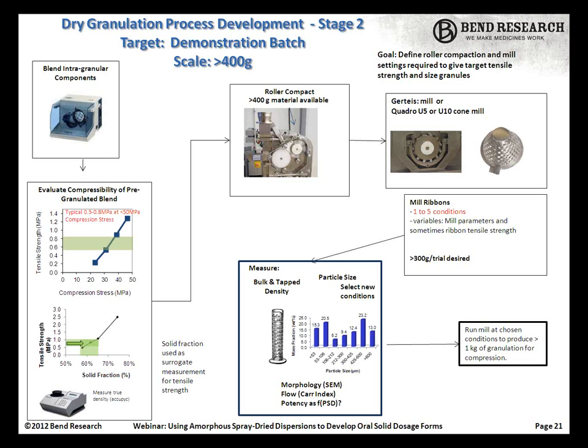So out of all of this, we now have the roller compaction roll forces, and the feed speeds and the ribbon thicknesses identified for what we need. We've identified the mill parameters to give us the target particle size of the granules. Of course, we characterize these for density and flow and morphology and so forth. But that then allows us to move into the tableting. The tableting process development is just straightforward.